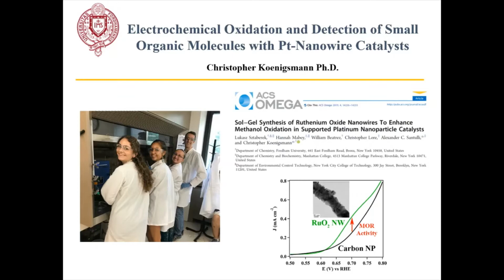So traditionally, the support material for typical catalysts is a carbon-based material like Vulcan carbon, Ketjen carbon. However, these traditional support materials tend to be inactive toward the electrochemical process itself. What we wanted to look at was how can we influence the oxidation mechanism by using a more active support like ruthenium oxide, which is a metal oxide. And there are several reasons why we chose ruthenium oxide. That's because of its high conductivity and its high proportion of oxygen at the surface relative to other oxides. And we wanted to see how this would affect the mechanism of oxidation.